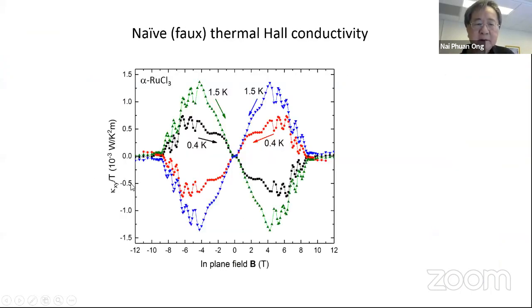As an example, if we took that butterfly curve seriously and converted it to thermal Hall conductivity, you see that below 3 Kelvin, you see a huge thermal Hall signal. This is all completely fictitious, right? And fortunately, we realized this before we wrote it up for publication.